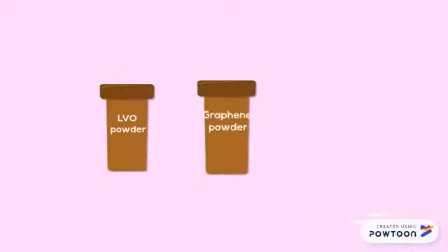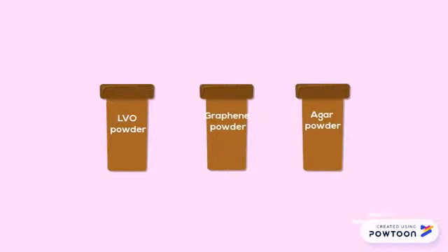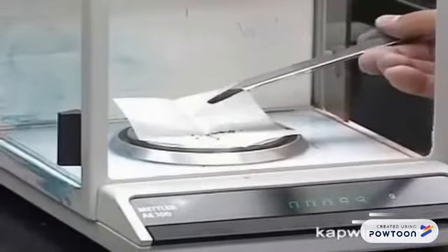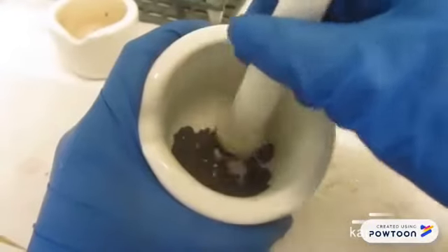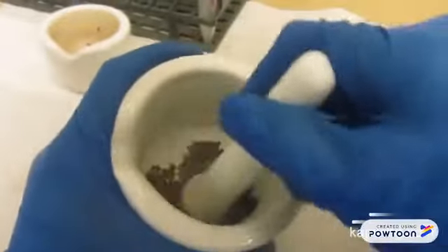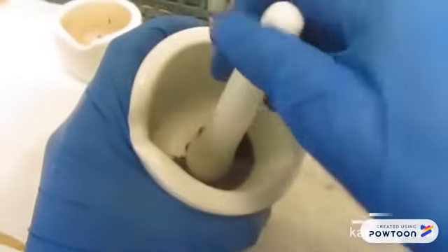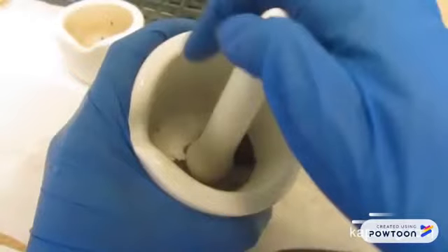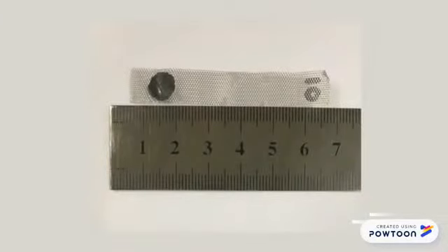To prepare the working electrode, LVO, graphene, and Agar binder in a wet ratio of 8:1 was measured. The wet percentage of the Agar binder for the anode varies from 0 to 20%, while the wet percentage of the graphene is fixed at 15%. The measured powder materials will be ground to achieve a homogeneous mixture, and in between, 1 drop of PTFE binder will be added to bind all the components together. The slurry will be formed into a circular shape before it is placed at the end of the stainless steel mesh.